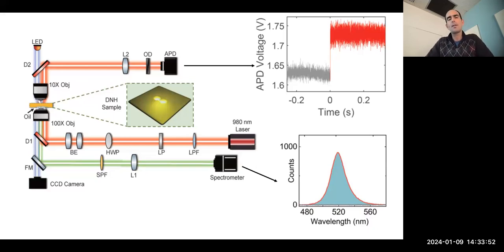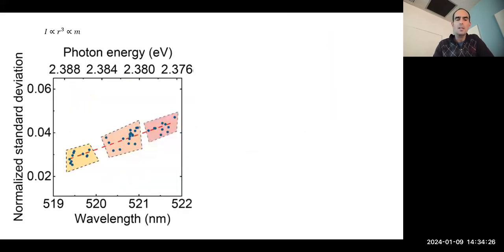One point I wanted to make is that we don't use an anti-Stokes sort of excitation scheme, we use a two-photon excitation scheme. So the wavelength we're exciting with is 980 nanometers, we absorb two of those photons and then get emission at 520 nanometers. It's two-photon absorption followed by spontaneous emission. We're not using a 400 nanometer laser in addition, so that really simplifies our setup a lot.